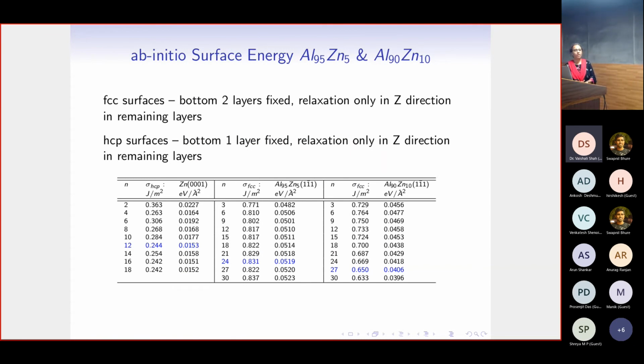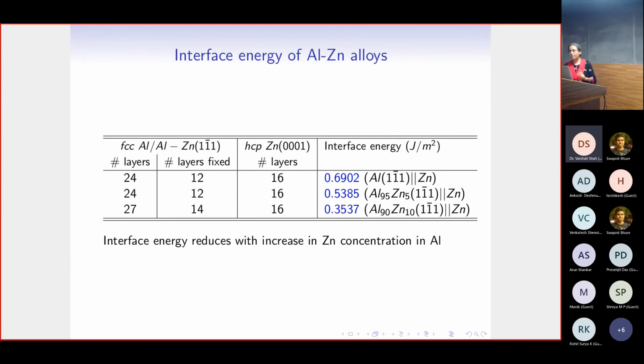We follow the same procedure again. Okay, we are going to fix the bottom two layers for the FCC and relax all remaining in the z direction to get the surface energy. Okay, and similarly for the HCP, same methodology. Okay, so now zinc has a very nice surface energy convergence behavior, but when we come to the alloy, we require a large number of surface layers as compared to the pure aluminum case to be able to see the good surface energy behavior. Okay, so with this now we have what is the thickness we should work with for the 95-5 and the 90-10. We go ahead with it, and now we do the interface energy calculation.